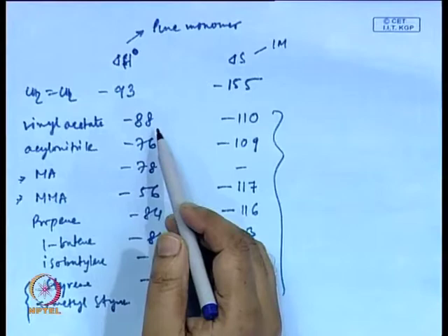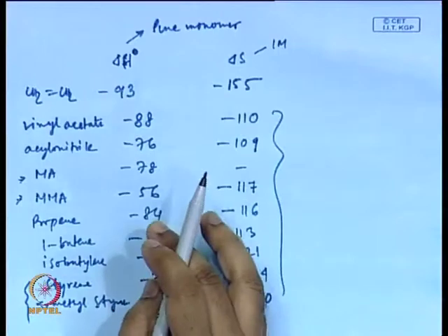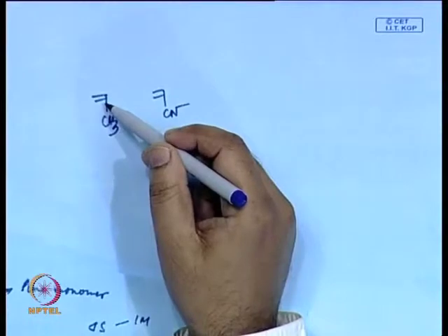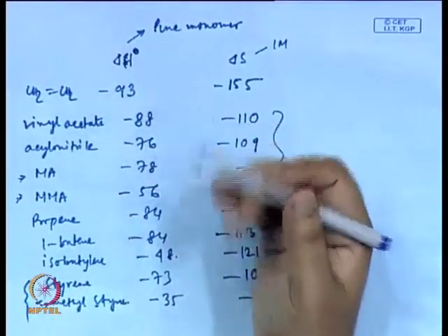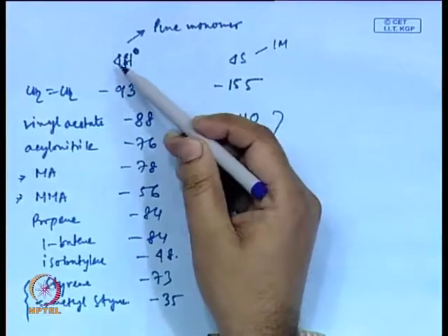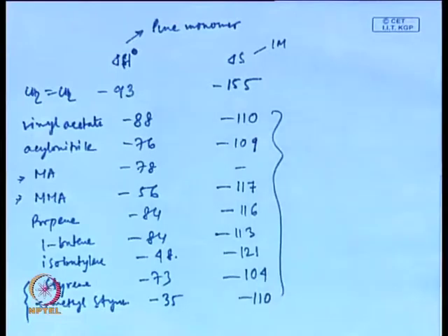So, that 76 compared to 84. Okay, so, anything you do to stabilize the double bond, it will lower the magnitude of the DelHp, and if you do anything which will increase the strain in the resulting polymer, that will also reduce the value of DelH, and as decrease in the value of DelH, which means thermodynamic feasibility will also come down.